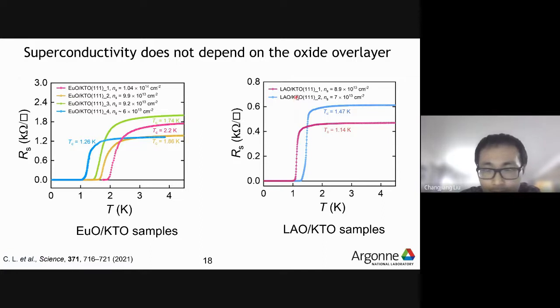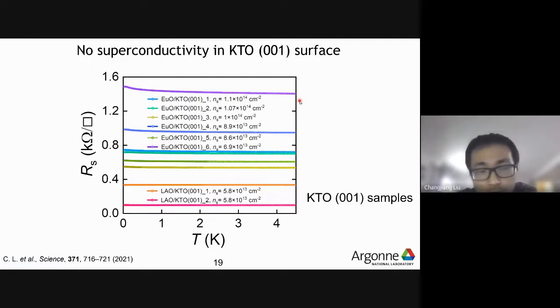So now you see that in both of these cases, the KTO substrate is 111 oriented. So we also investigated KTO 001 surface, and in this plot we have several samples, all of them grown on the KTO 001 surface, including both europium and lanthanum aluminum oxides. And in all of these samples, we do not observe any superconductivity. So this means the superconductivity is very interesting in that it cares about the crystalline orientation.